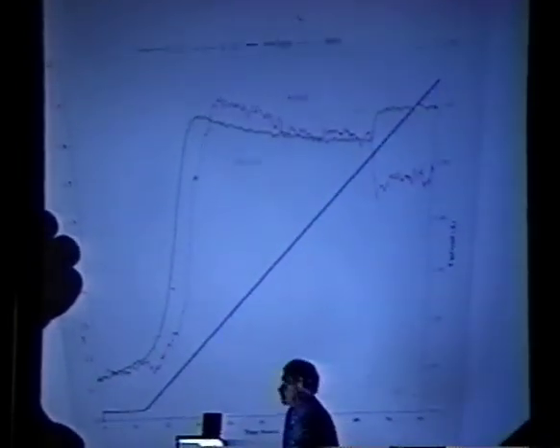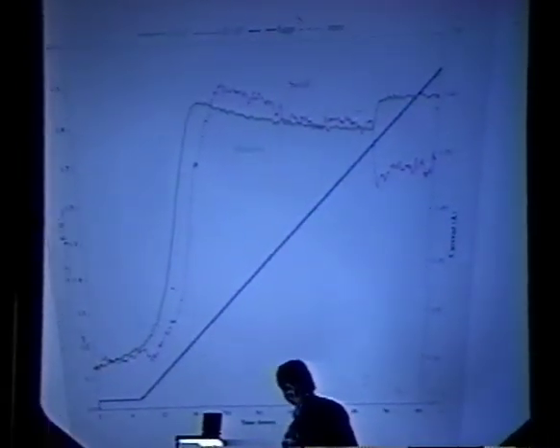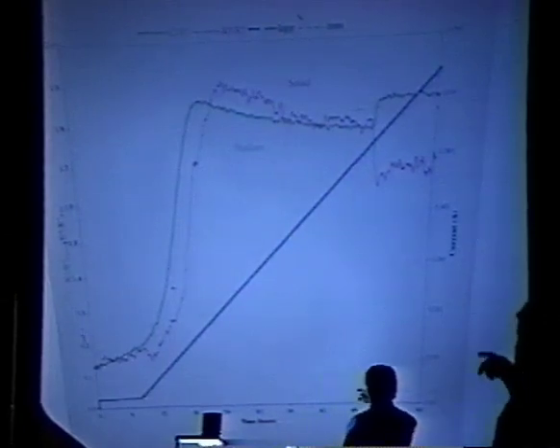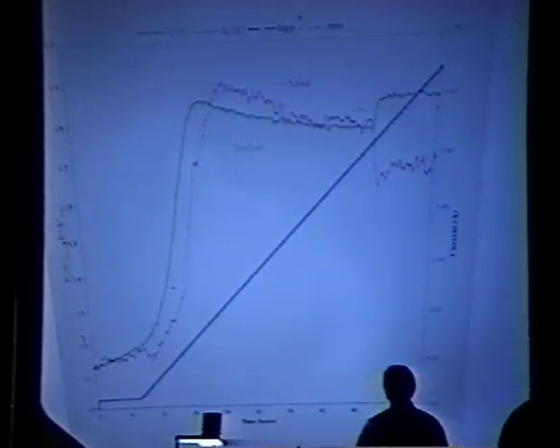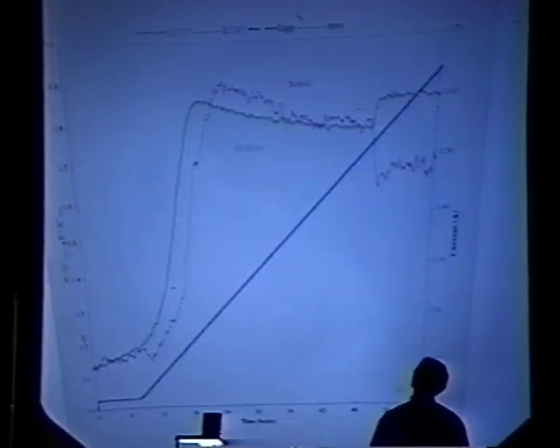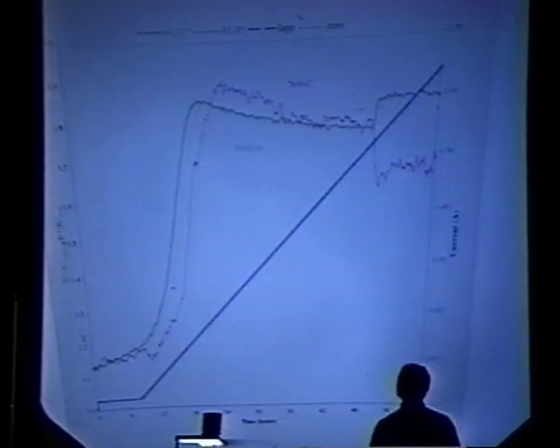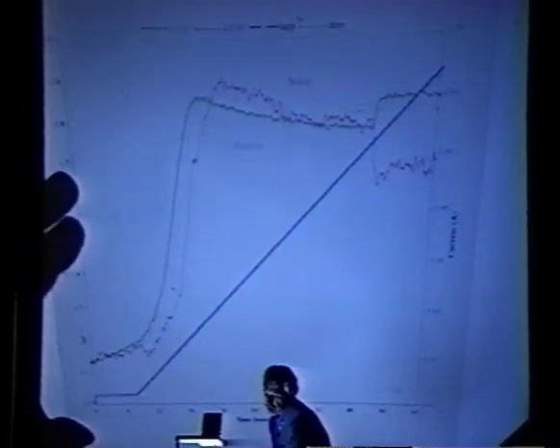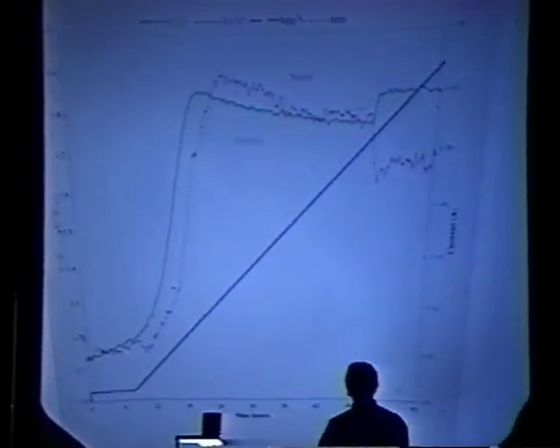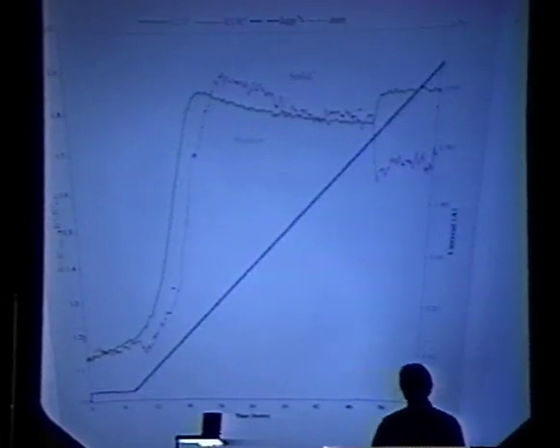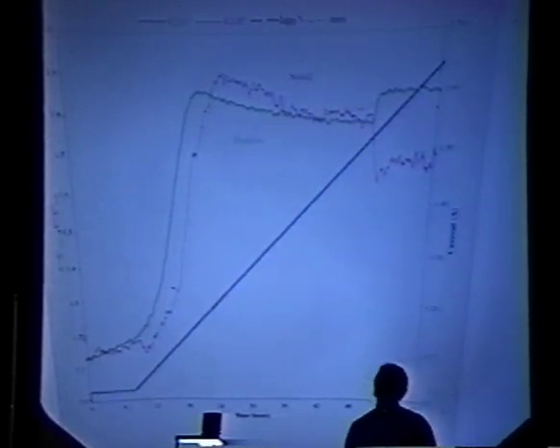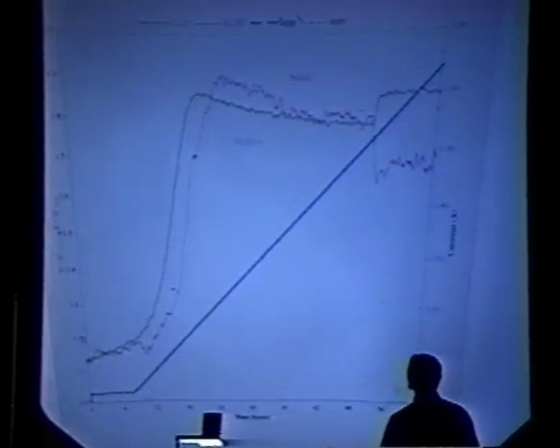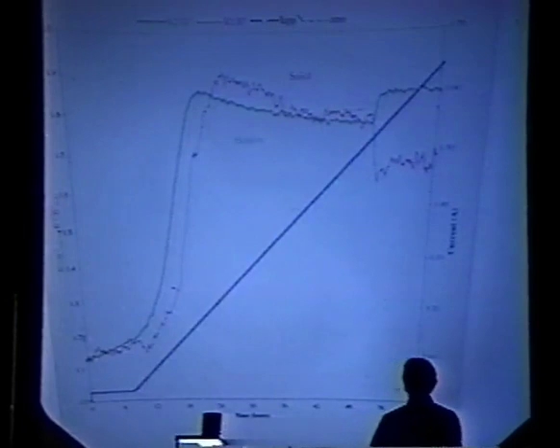We have some independent evidence, very recently obtained in fact, that this mechanical disruption does occur and does prevent us obtaining high loadings. What we're doing is working along the lines suggested to us by Professor Arata and Dr. Zhang, of a double structured cathode. That is a palladium cathode in our normal mode, 4 millimeters outside dimension, drilled out, with a 2 millimeter hole packed with palladium black and then welded closed.